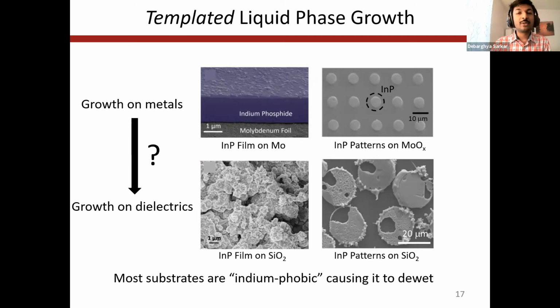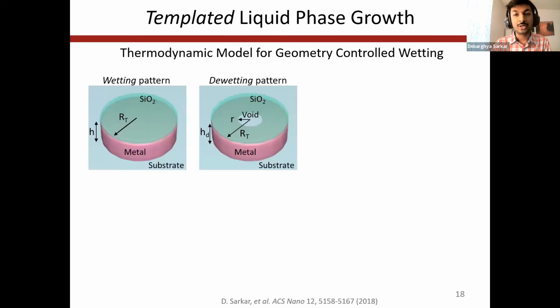To understand this phenomenon better and to see if we can have a control over the wetting propensity of different liquid metals on different substrates, we worked on a thermodynamic model where we calculated the Gibbs free energy of two different structures, one which we call the wetting pattern, where the liquid metal, such as indium, when it is molten, is wetting the entire surface area as intended. Another is a de-wetting pattern where it's not, instead a void is formed, similar to what was shown previously.